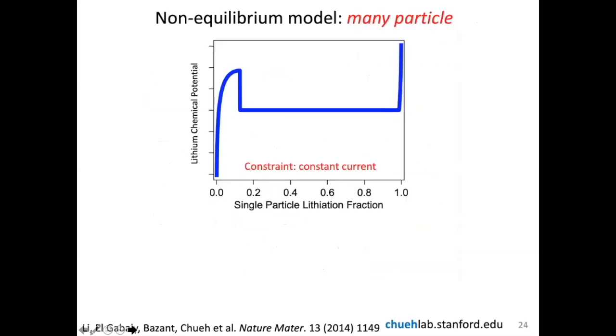So what's going on here? Well, it turns out this has everything to do with kinetics and thermodynamics. So when you have many particles in a system, you have to think about the behavior not only within a particle, but between particles as well. So this is a classical nucleation and growth problem. For something like lithium iron phosphate, you have a large miscibility gap of two-phase coexistence, and you have a nucleation barrier. So what happens is, in order for you to maintain a constant current, for example, as you discharge the material, you have to have a certain driving force to overcome the nucleation barrier. But in order for the nucleation to happen at a finite rate, you need to keep the driving force there. But as the driving force is kept there, that means as you enter the two-phase regime, you have a fixed driving force causing the phase transformation to occur.